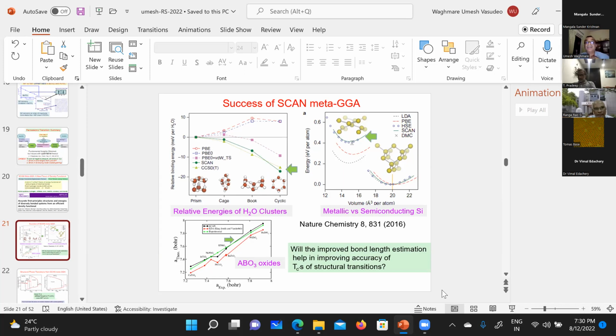Most certainly. High entropy alloys are again a challenging problem, and what we did is what is possible within our computational resources. But certainly we can do the same thing for oxides. The cost of computation may be marginally higher because you have additional oxygen atoms, and probably in these oxides it's the cation which has multiple elements, or that's what I would expect. Sometimes they also look at vacancies in these high entropy oxides, which seem to give very interesting properties for certain applications. Thank you for pointing that out. That's certainly interesting to us, and it should be exciting to look at.